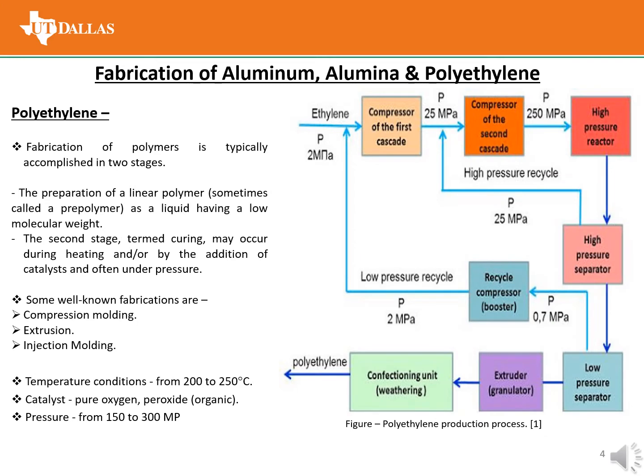Some fabrication techniques are compression molding, extrusion, and injection molding, and there are two steps in the fabrication of polyethylene. At the first stage, a linear polymer is prepared as a liquid having a low molecular weight, and then curing is done. The whole process is shown in this picture. Temperature is set from 200 degrees Celsius to 250 degrees Celsius, pressures are 150 to 300 megapascal, and catalysts are pure oxygen and peroxide.